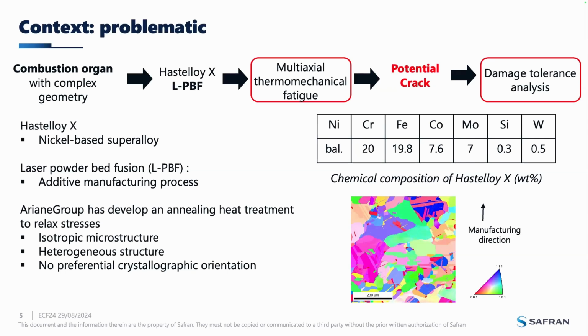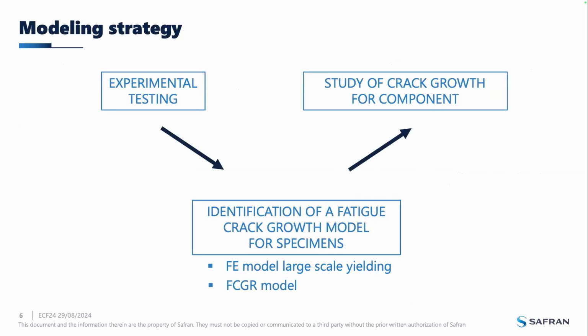That is why Ariane Group has developed an annealing heat treatment to relax stresses. And as you can see on the IPF map, according to the manufacturing direction, the microstructure is well isotropic, heterogeneous, and there is no preferential crystallographic orientation. So it seems successful. The aim of my study, based on experimental testing, is to identify a crack propagation growth model for specimens, and then to scale up and study crack propagation for the components.